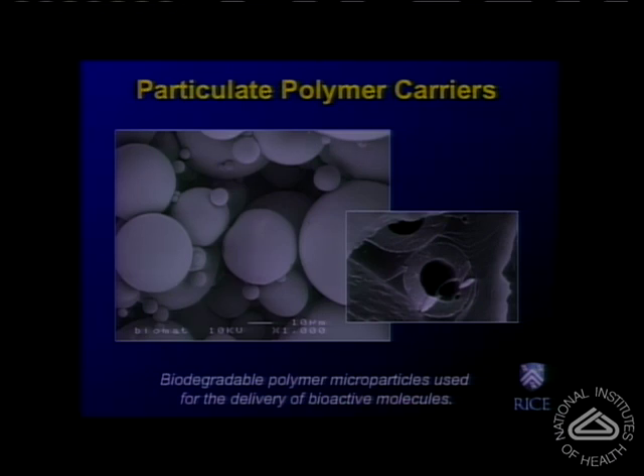What we see here in this slide is biodegradable microparticles that can be loaded with a growth factor. And these microparticles can release a bioactive molecule in a controlled way. They can be physically loaded or placed within the pores of the scaffold, or can be embedded within the bulk of the scaffold as needed as part of a tissue engineering strategy.